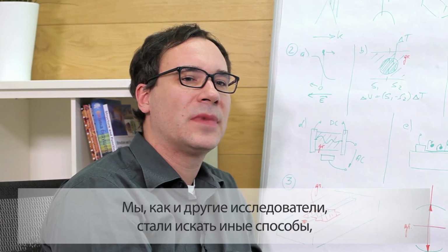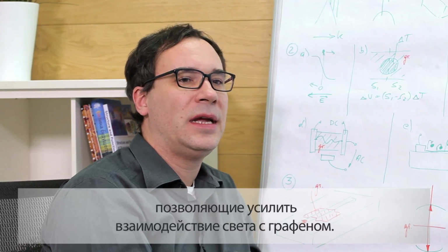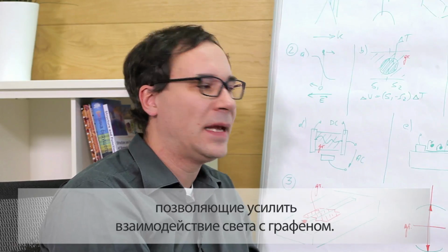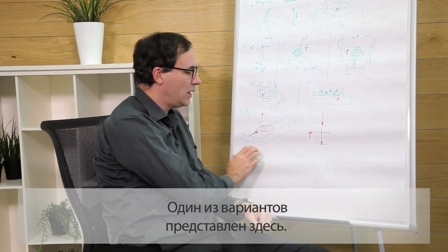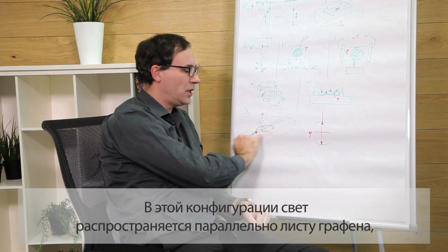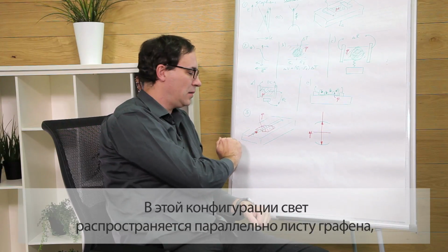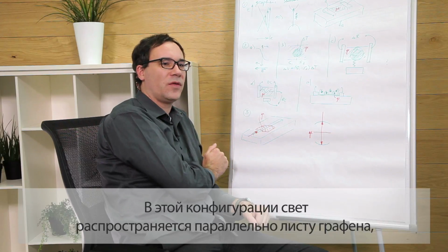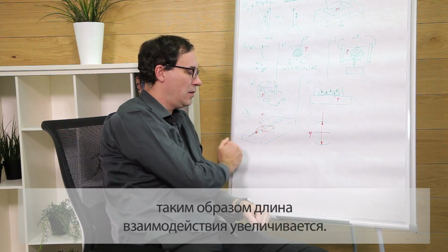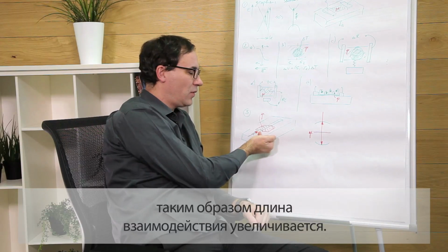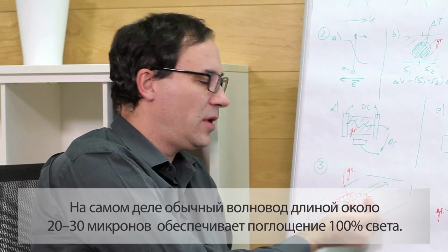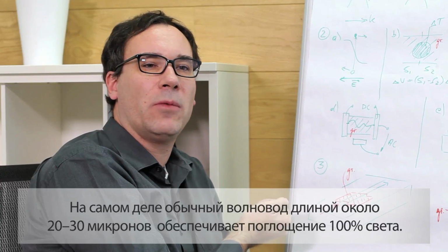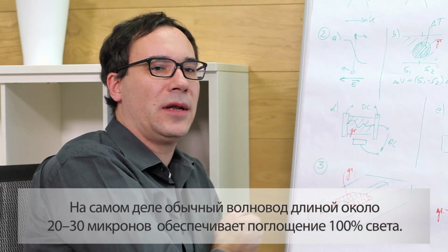So people started, including us, to look at different kinds of geometries to enhance the interaction between light and graphene. And one of those mechanisms is shown here. The light in this case is not propagating perpendicular to the graphene sheet, but it's propagating in parallel. So you can make the interaction length between graphene and light much longer. In fact, you need something like 20 to 30 micrometers in a typical waveguide to absorb 100% of the light. So you can increase the absorption of light and increase the responsivity of your photodetector devices.